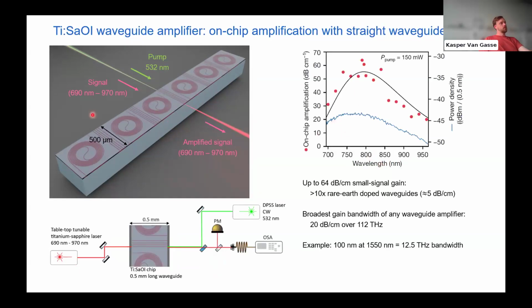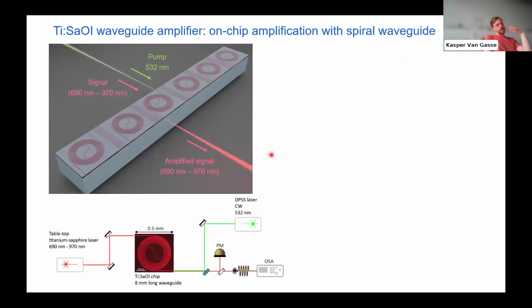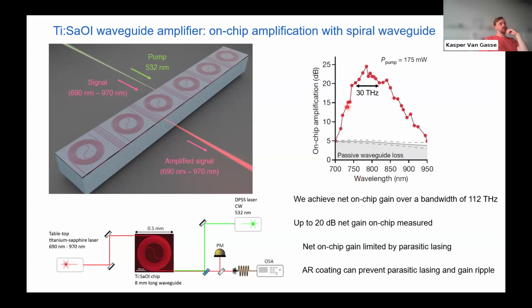And so this was just to extrapolate the gain per unit length. But of course, we also want to make an actual amplifier that can amplify signals in a very compact form factor. Interesting to note is that this spiral waveguide is really only 0.5 millimeter by 0.5 millimeter, so extremely tiny. This is a fraction of any photonic integrated circuit, so you can put tens or even hundreds of these amplifiers on a single chip. However, it can provide extremely high gain over an extremely wide bandwidth.